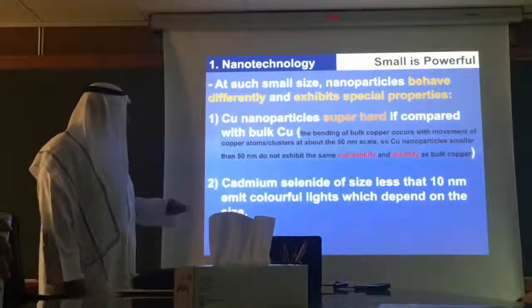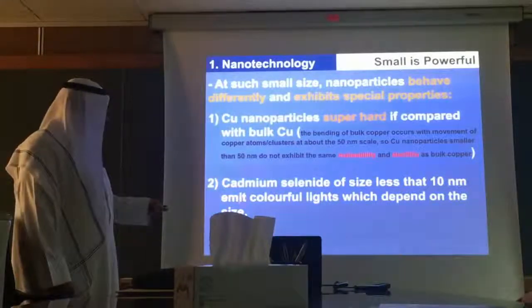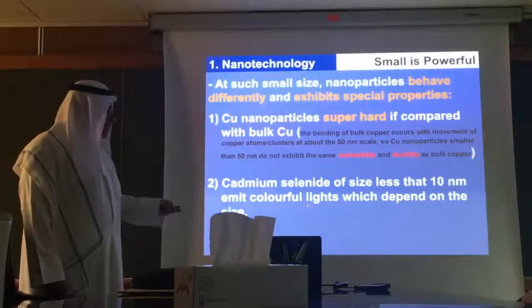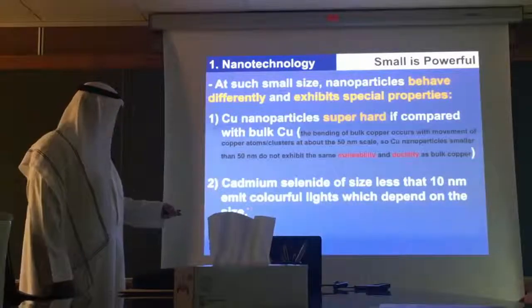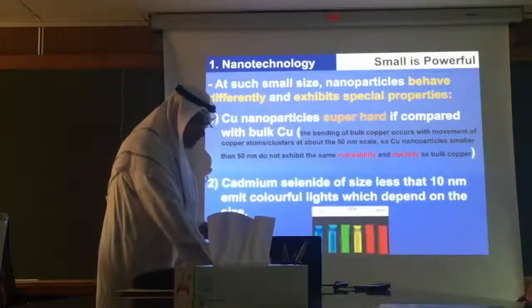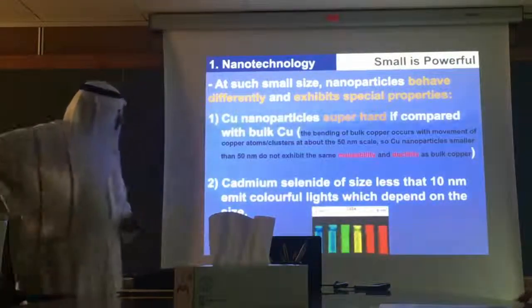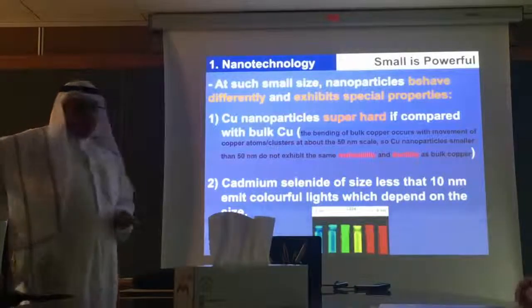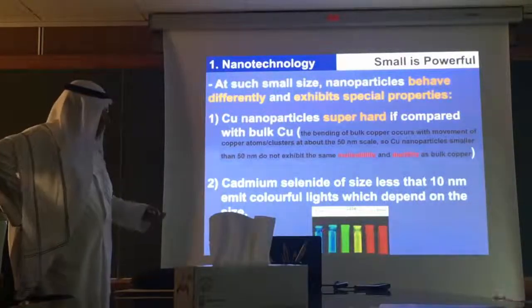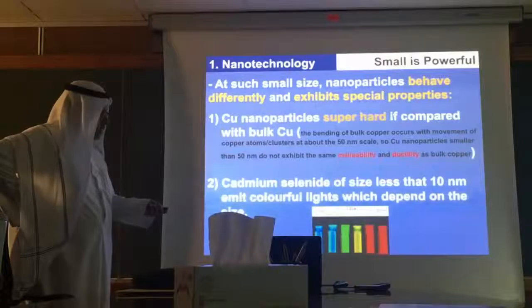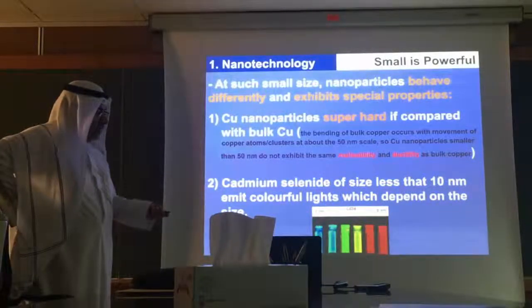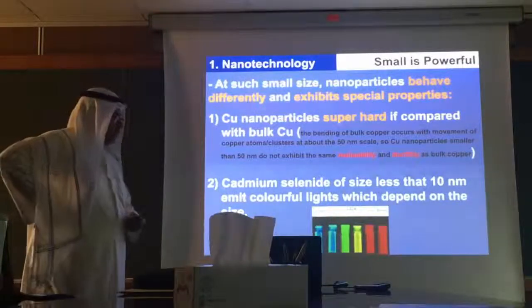Cadmium selenide, I told you, if the size is less than 10 nanometers, it will emit colorful light, which depends on the size, and this is what we call confinement or the quantum dot. This is cadmium selenide samples from 2 nanometers to 8 nanometers. You can see how the color changes just by changing the size of the particles.